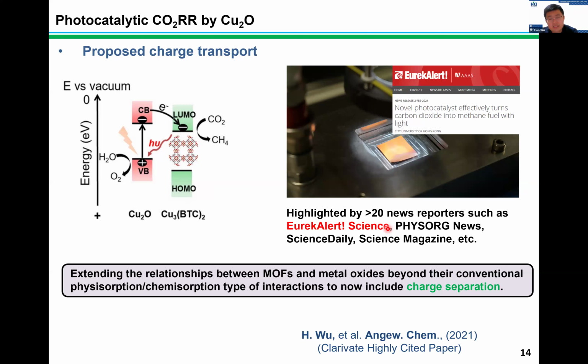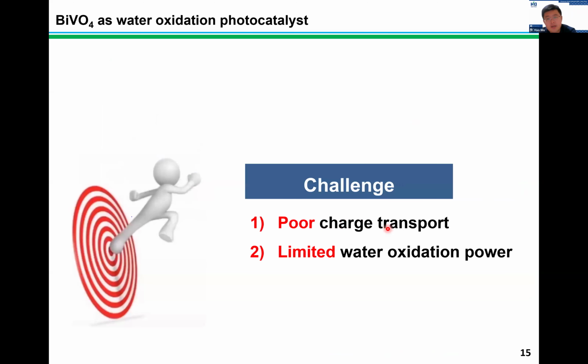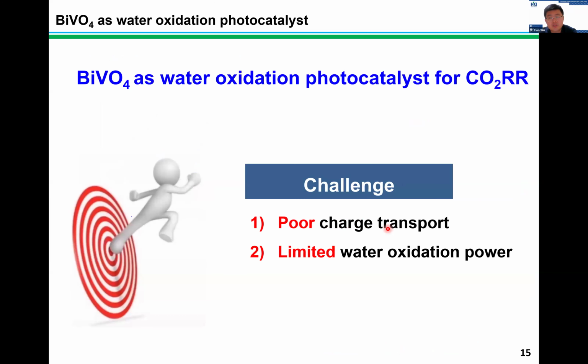But regarding the activity, our performance is still low. And we found that in such a process, the overall efficiency of our system is still limited by the poor charge transport of photo-induced holes and also the limited water oxidation power of cuprous oxide. So to further improve the performance of our system, we try to assemble another water oxidation photocatalyst with our system to improve the carbon dioxide reduction reaction performance. And we select the benchmark material bismuth vanadate. But before we assemble the bismuth vanadate into our system, there is plenty of room for us to investigate different types of bismuth vanadate and select the best candidate.